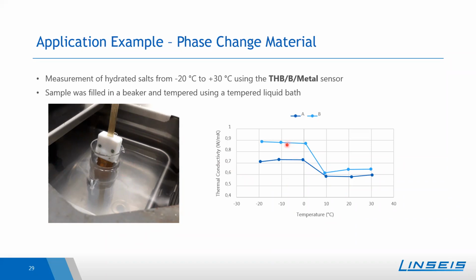Here you can see the resulting thermal conductivity, which each shows the average of 3 measurements at one temperature. What is clearly visible is that the thermal conductivity changes with the state of the material. So at room temperature and below room temperature, it was liquid, and below or around 0 degrees Celsius, it started to be solid. And here the thermal conductivity each is higher for the solid state compared to the liquid state. So with this application example, you can see that the measurement of a solid and a liquid can both be realized with the THB.